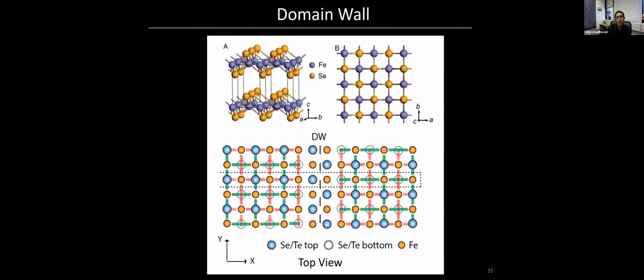So here's the idea. This is the top view on one side of the domain wall. These are the top selenium atoms. And on the other side of the domain wall, the crystal has simply flipped over. So then what you expect to see is a half unit cell shift of the top atoms. This is the top atoms here, and these are the top atoms here. This is the domain wall. So you expect to see a half unit cell shift. And if you can find such a domain wall, then at least theoretically, you have all the ingredients necessary to